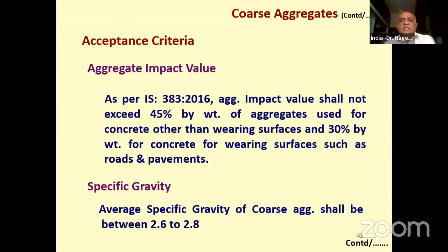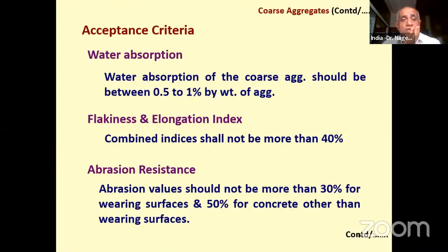For all these tests, the requirements are there. So these requirements can be verified, and these requirements can be checked. Water absorption of aggregates will not normally be high, about 0.5% to 1%, or sometimes less than 0.5%. Flakiness and elongation index combined shall not be more than 40%. This is what IS-383 gives.